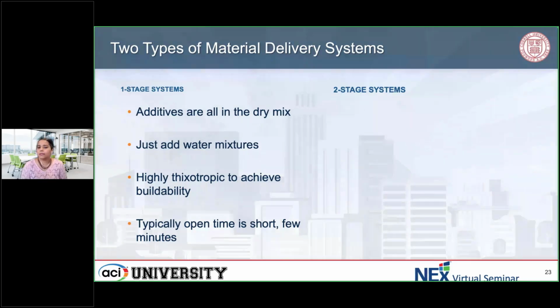The other thing with the one-stage system is that obviously you need to have this dry mix mixed really well within the bag. You don't want any segregation within the dry mix. So typically these have to be designed really well. But in our lab, we don't have the capability of doing the dry mix on the large scale. So that's why we prefer the two-stage system.